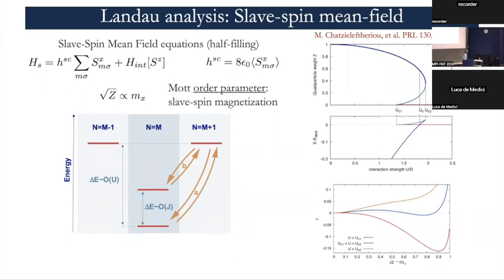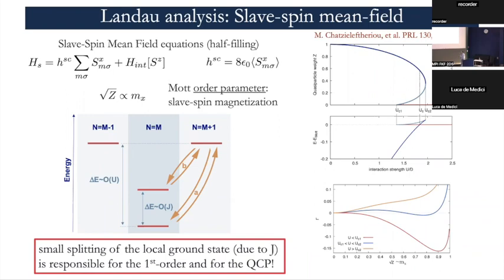So, to the fact that the ground state in the charge sector, which is the fundamental charge sector above which you have charge fluctuations in the metal, which are blocked or substantially reduced in the Mott phase, well, the ground state is split by a small amount, and this small amount is Hund's coupling, and you can actually show perturbatively that these processes are responsible for the first order character that comes up in the Landau theory. And that's very general. You can split the ground state of the charge sector where you create the Mott insulator in different ways, like with crystal field, negative J, and in all cases you should end up getting an electronic transition of the first order, and all that follows.